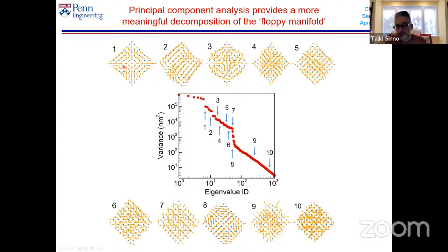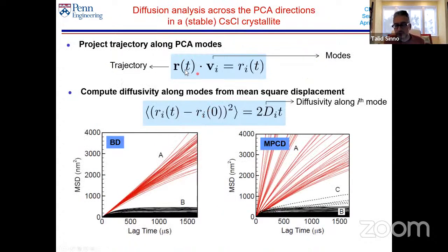And now we can take all of these well-organized, or relatively well-organized, modes and ask, how does the system evolve along each of these modes? So what we did is we took the trajectories and projected them along each of these modes. If you do this, you can compute diffusivity along each of these directions. With Brownian dynamics, what you find is there are 2 types of trajectories: trajectories that have high diffusivity, and trajectories that have low diffusivity. But all the high diffusivity trajectories have the same slope at early time.